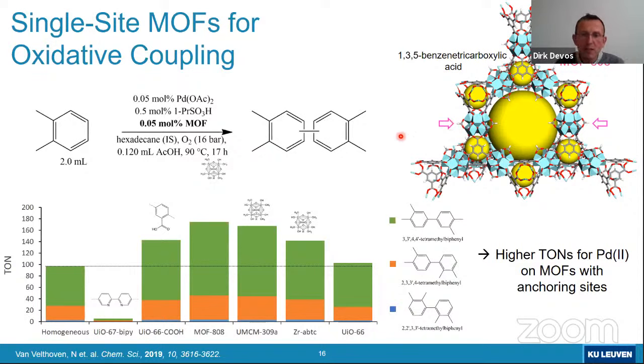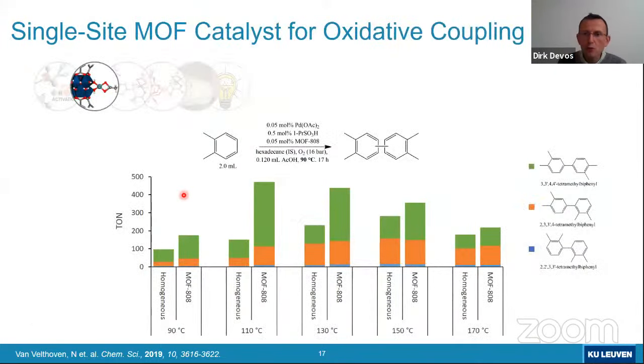So indeed, we saw that there was this positive, this stabilizing effect of the MOF on the activity of the palladium. And that's also shown here in this graph. Here we actually compare this for a number of temperatures. And then you see that over the whole temperature range, consistently we see superior turnover numbers when the palladium is sitting on the MOF-808 in comparison with the homogeneous case. And depending on the temperature that you consider, the effect is actually quite large. The palladium on the MOF does 3 times as many turnovers as the homogeneous catalyst.